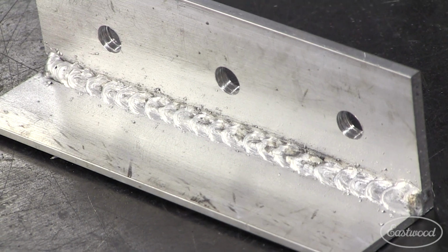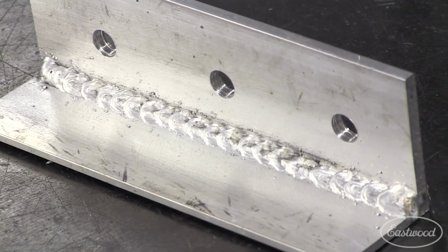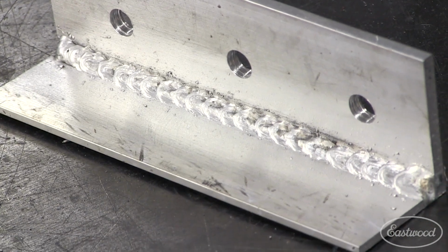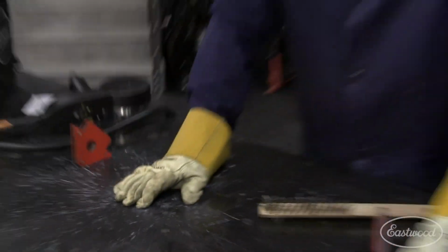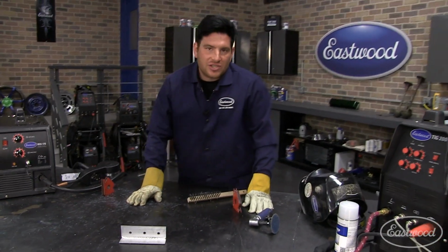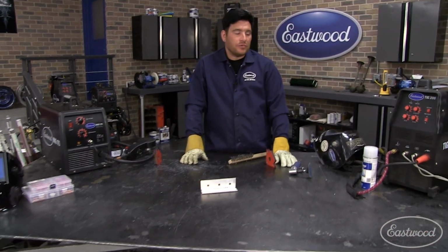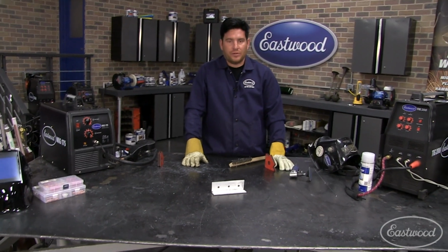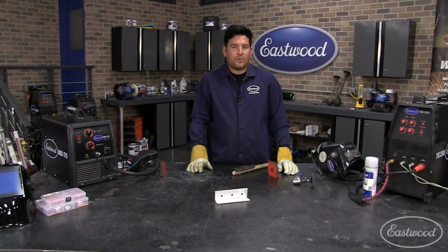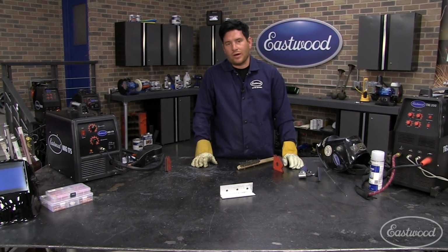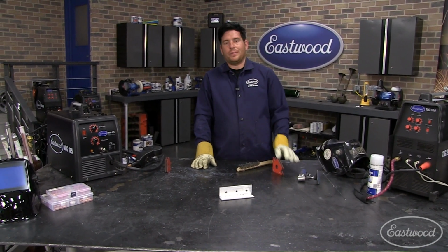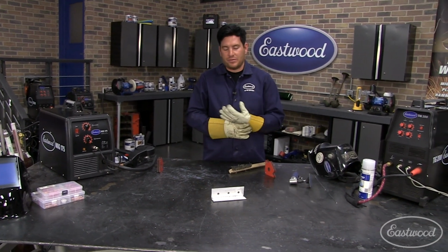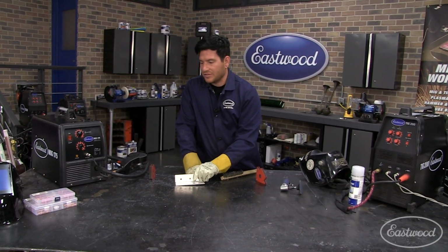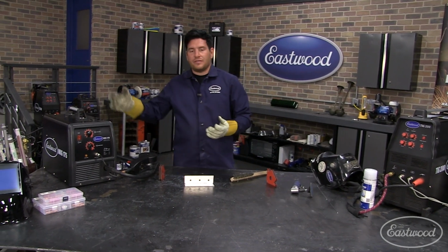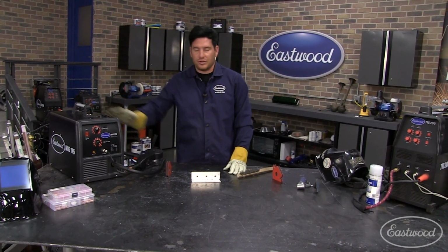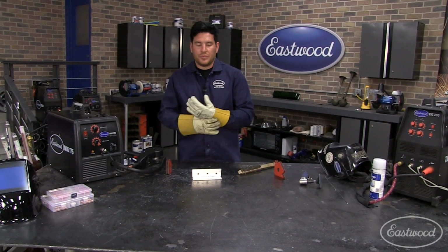The times that I'd use a MIG spool gun over a TIG welder, you can get into tight spaces that you may not be able to get into with a TIG welder. If you're welding something you just can't get clean enough, with a TIG welder you'll probably fight it and won't be able to really get a weld. With this, you can at least get away with something that's a little dirtier. It may not be as pretty as you'd like, but you can still lay a weld down somewhere that a TIG may not be able to at all. So it does have its advantages, and obviously the advantage is that you don't have to buy a different machine. You can just have your spool gun on hand, and you can use your MIG welder.